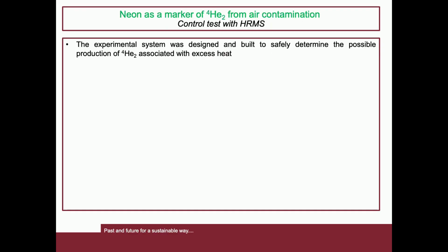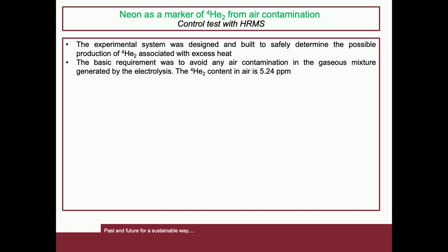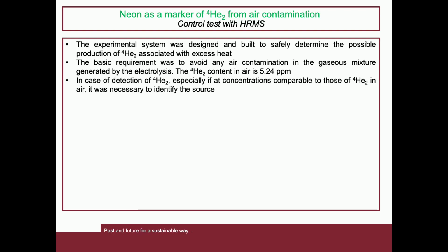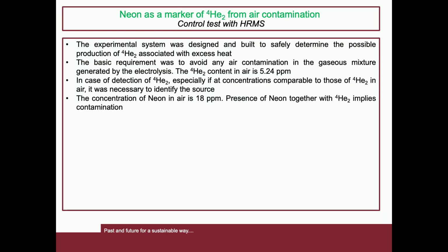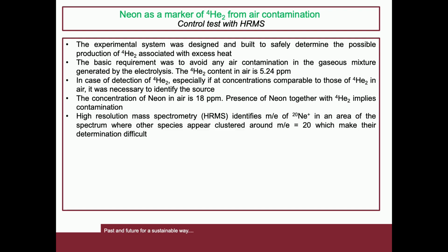Neon as a marker of helium-4 from air contamination. The experimental system was designed and built to safely determine the possible production of helium-4 associated with excess heat. The basic requirement was to avoid any air contamination in the gaseous mixture generated by the electrolysis. The helium-4 content in air is 5.24 ppm. In case of detection of helium-4, especially at a concentration comparable to that in air, it was necessary to identify the source.